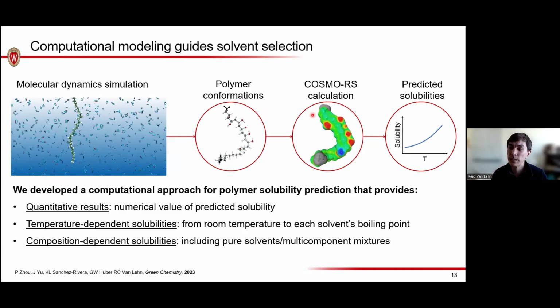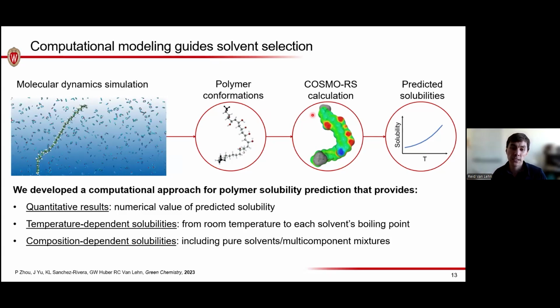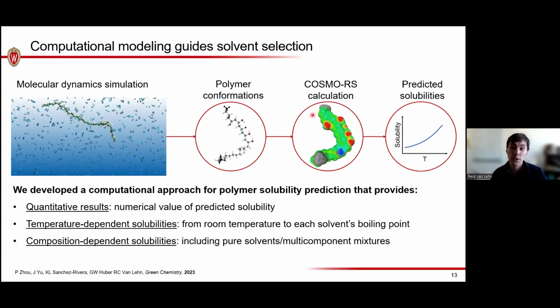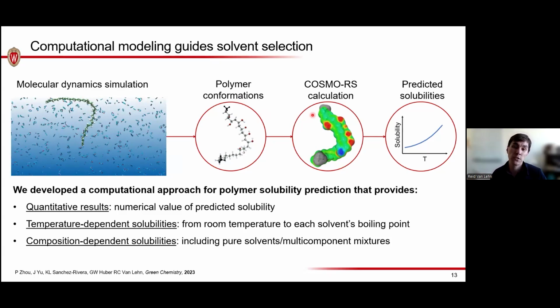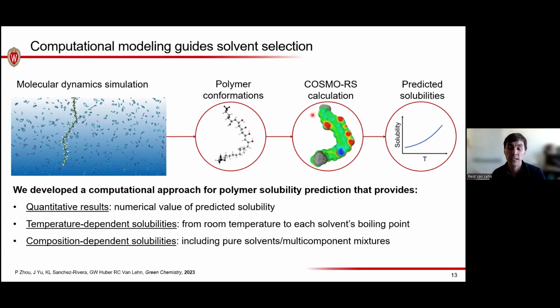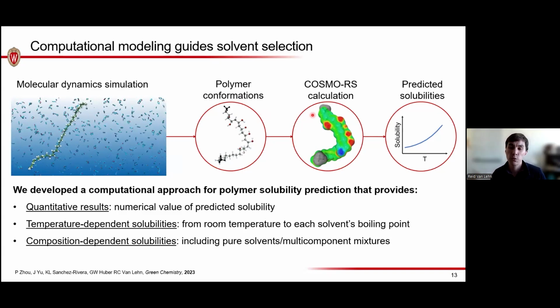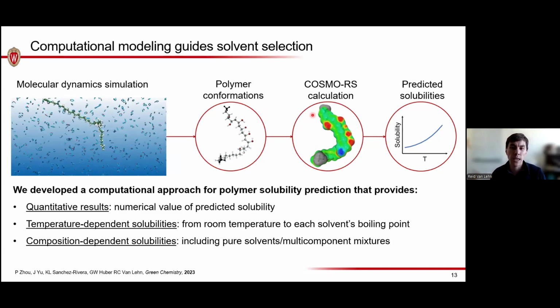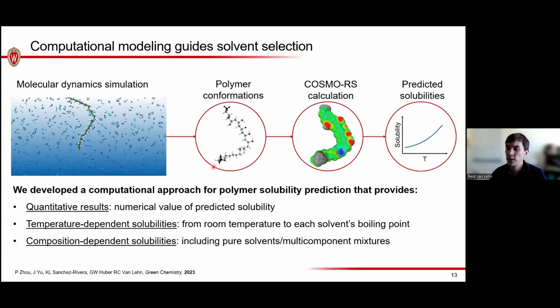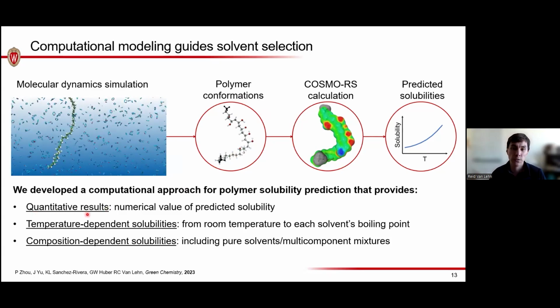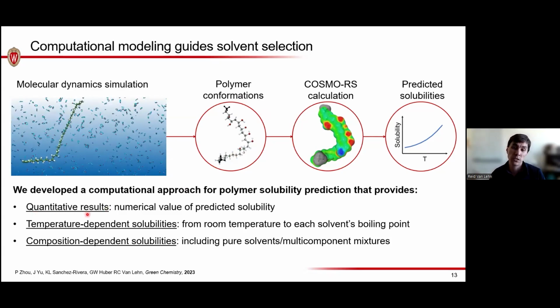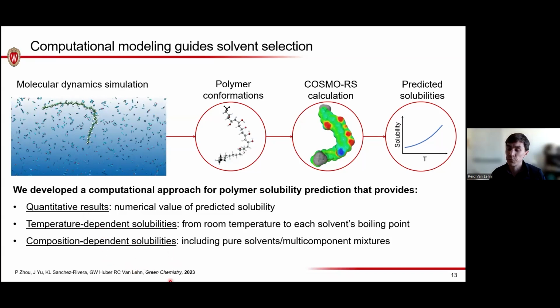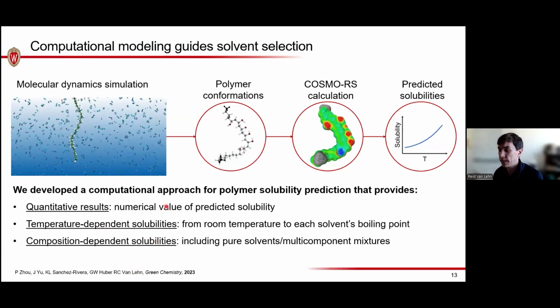The reason that we need to do this is because of the many different polymers possible, there could be dozens to thousands of different solvents that we might have to assess to see whether or not the polymer is soluble. So we've generated a database at this point with 11 polymers and about 1,000 different solvents that have numerical values of our predicted solubility as a function of temperature. That's been published and is freely available as part of that citation.